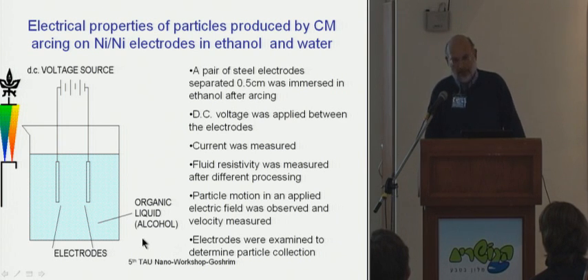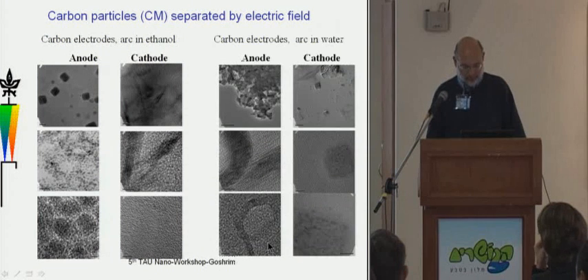What we did is, after all of the arcing, we put in another pair of electrodes and placed a low voltage battery, if you will, between the two electrodes, and observed, first of all, that there is conduction, even though we're talking about alcohol, which is presumably non-conductive. We can measure the current, and particles would collect on these two electrodes, which basically indicates that the particles in suspension carry an electrical charge. And then we looked at the particles that were collected on the electrodes, and they were quite different.